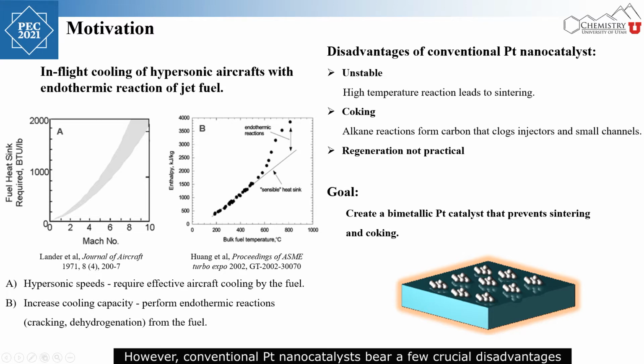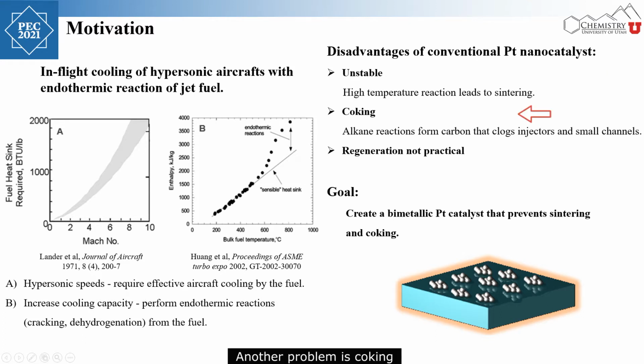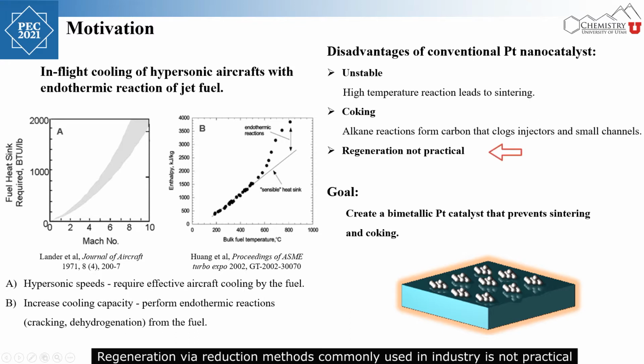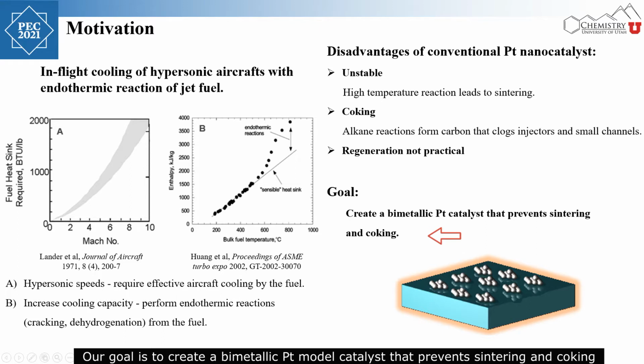However, conventional platinum nanocatalysts bear a few crucial disadvantages. For example, the catalysts are unstable, as high temperature reactions will cause sintering. Another problem is coking, where alkane dehydrogenation will deposit carbon over injectors and small channels inside the aircraft, causing unwanted issues. Regeneration via reduction methods, commonly used in industry, is not practical, as this also involves high temperature reactions which will lead to sintering. Our goal is to create a bimetallic platinum model catalyst that prevents sintering and coking.